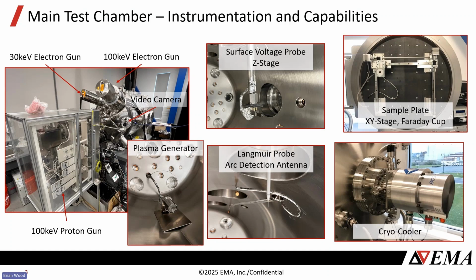Also in that top right, you see an XY stage that we can use either for specific probes, like there you're seeing the Faraday cup mounted to it, which we use to map out the radiation sources, or we could use that for sample manipulation or anything else we need. Finally, we also have a cryocooler, so we have the capability of mounting the sample fixture to the end of that cryocooler, and that would allow us to do some cold temperature testing without power load. That would essentially get down to 40 Kelvin if we wanted to. And that's something our customers are also eager to use for their projects.